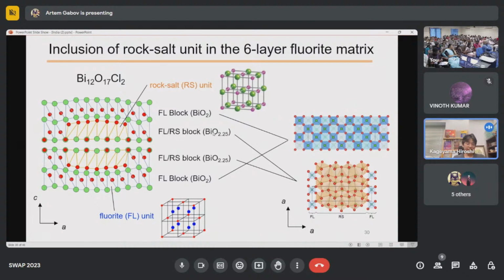So as I mentioned, we thought that this structure should have a 6-layer fluorite block, but we found that this is not a pure fluorite structure, but a mixture of the fluorite structure and the rock-salt structures. As you can see here in this orange region, a kind of rock-salt block, a kind of one-dimensional block, is inserted in this 6-layer fluorite structure. That's why this gives rise to the modulation of the crystal structure.